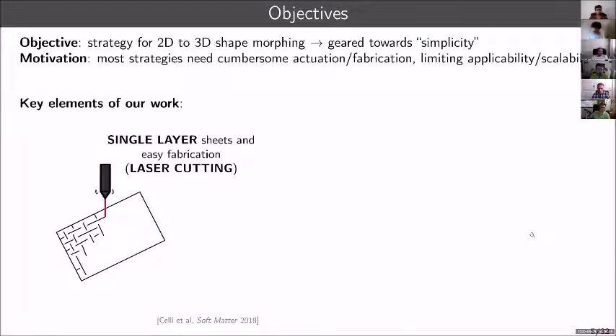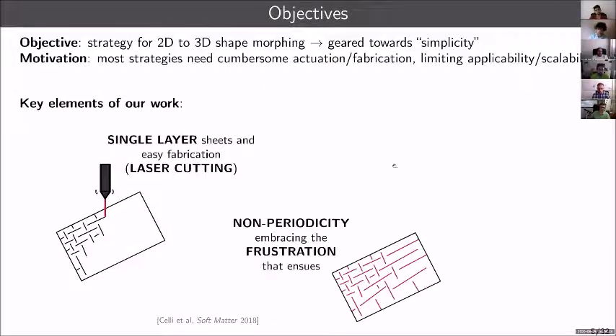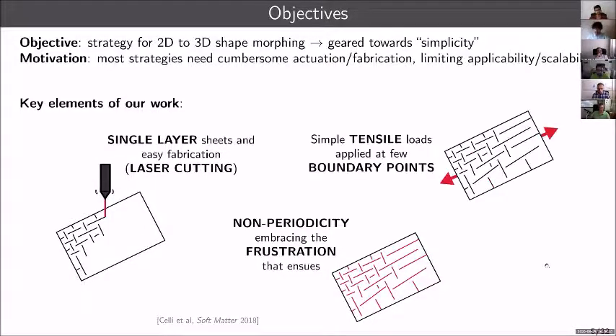Our system presented the following key elements. First of all, we use single layer sheets and we use laser cutting in order to imprint a certain cut pattern. Our cut patterns are non-periodic, and at the time we were among the first that tried to actually use non-periodicity in these metamaterial systems. And finally, we used tensile loads, applied at a few boundary points in order to trigger the actuation.